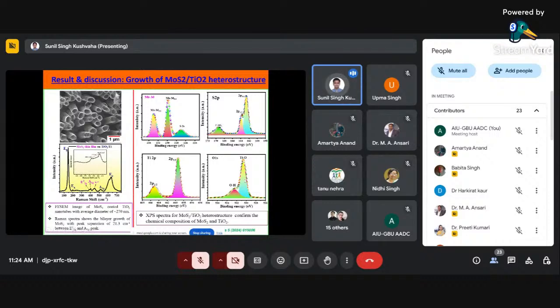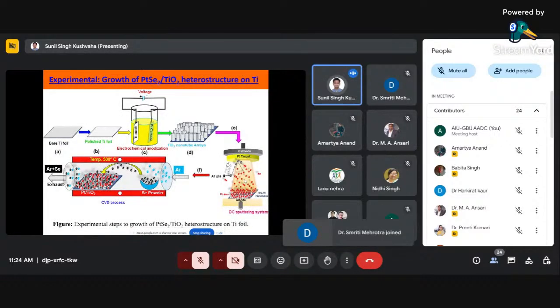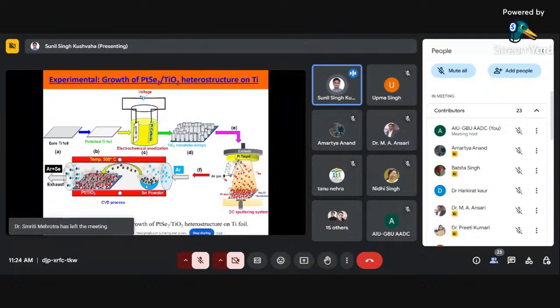So of course we know the materials has been formed, we know the structural quality. Now we have to use this for the photoelectrochemical cell. So same thing, as I mentioned, it is different process required for the different 2D materials growth. So for example, here we again grow some this PtSe2. This is the one of the 2D materials. So again, here the same procedure we have. Like we have this titanium foil, then we use this electrochemical analysis. After that, we grow some platinum using this our sputtering system, and then after that, we again do the selenization.